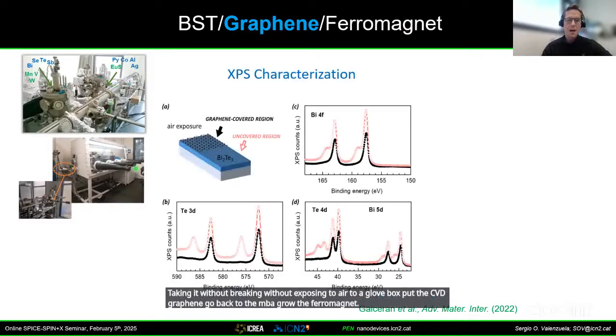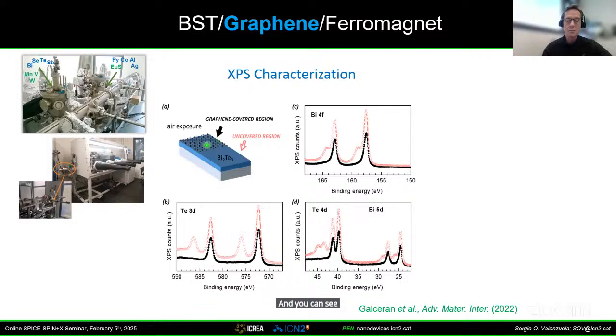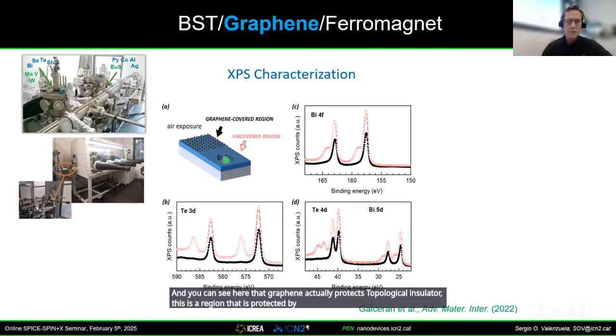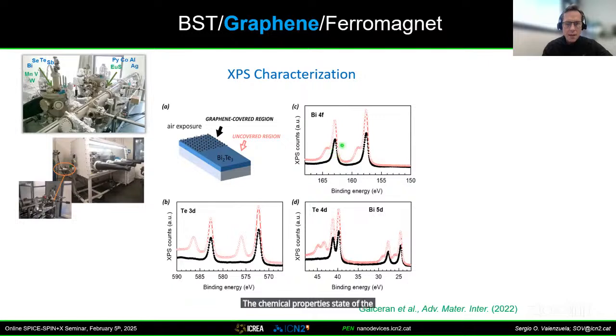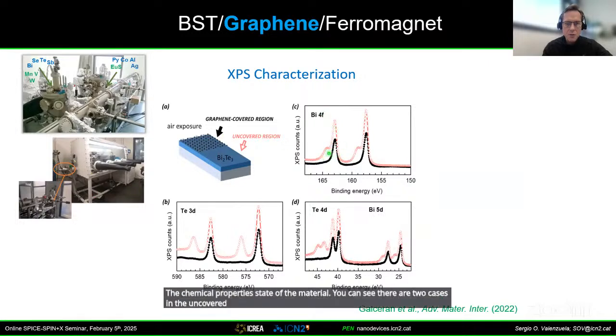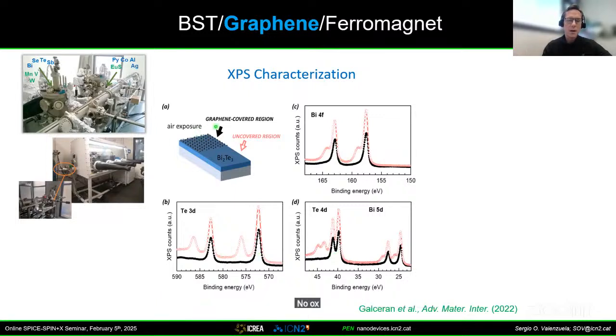These are done by growing in the MBE, taking it without exposing to air to a glove box, put the CVD graphene, go back to the MBE, grow the ferromagnet. And you can see here that graphene actually protects the topological insulators. This is a region that is protected by graphene. This is a region that is exposed to the air directly. And by looking at XPS, I will not enter in details, but the XPS actually tells you the chemical properties, the state of the material. You can see there are two cases in the uncovered region for bismuth, 2 peaks, and this indicates oxidation. In the case that is covered, there is no oxidation, and the same happens with tellurium and all of the other peaks. No oxidation with the air exposure.